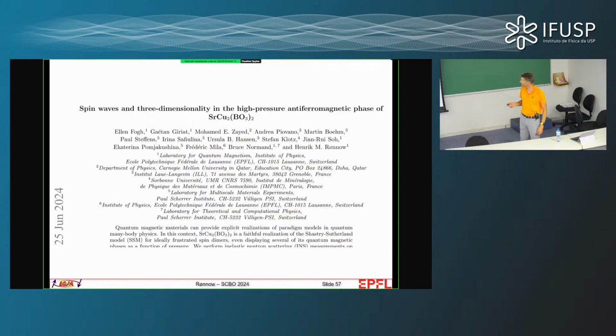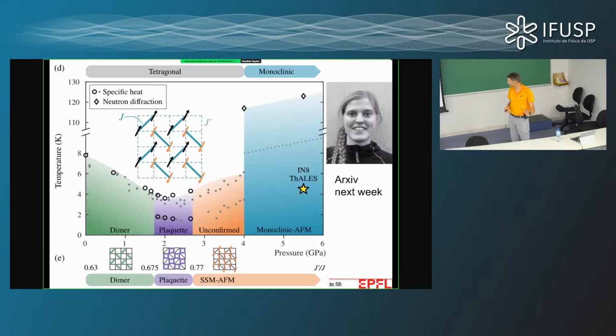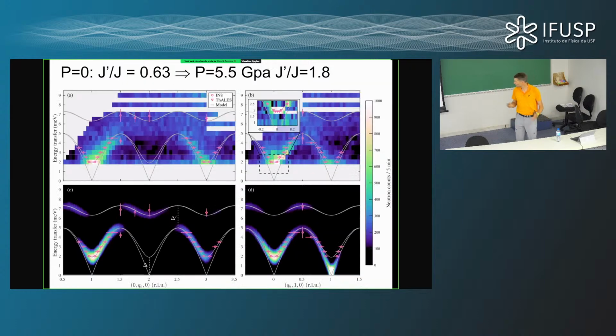But we're not sitting still. Actually, you will see that the day before yesterday, we put something on the arXiv, which is about this very high pressure antiferromagnetic phase. And with that, I promise I will stop. So I've told you about the dimer phase. I've told you about the plaquette phase that we found. Now, if you go all the way up here and you actually turn the crystal from a tetragonal to a monoclinic crystal structure, you create long-range antiferromagnetic ordering. So to some extent, it's more boring. But if you can do it, then why not?